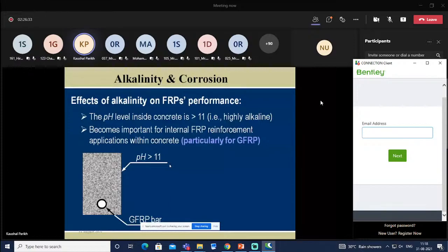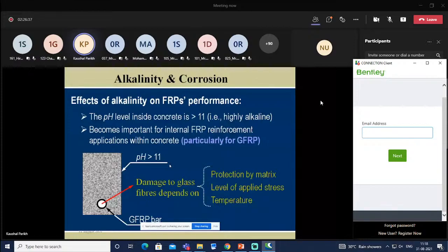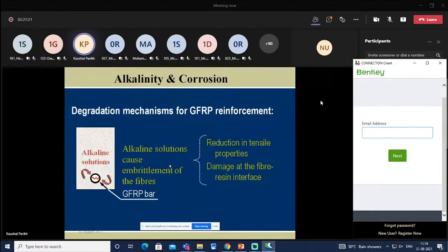Because the pH level is greater than a certain range, a favorable environment for alkalinity will be created, and because of that there is damage to the glass fibers as far as the reinforcement is concerned. Here it depends on the protection by the matrix level. It affects the glass fiber, but we have to check what the protection of the matrix on that particular fiber will be. Now, degradation mechanism for GFRP reinforcement. See the typical image over here. Alkaline solutions cause embrittlement of the fibers in the GFRP bar, cracks will be created, and there will be a reduction in tensile strength properties that will also damage the fiber resin interface.